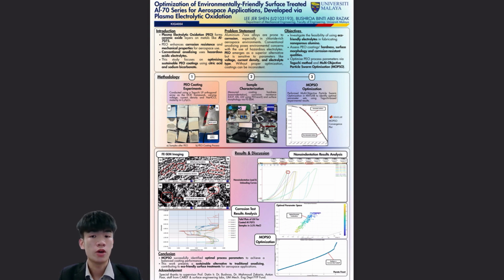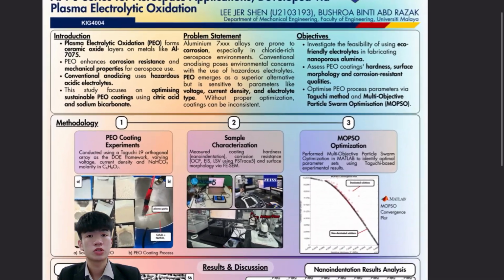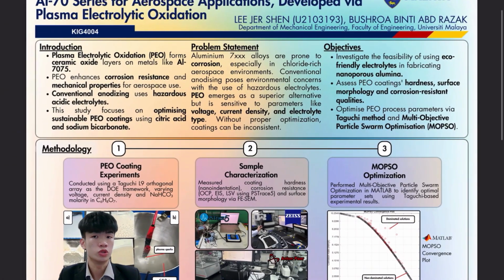Aluminium 7075 is widely used in aerospace applications due to its high strength-to-weight ratio and fatigue resistance. However, it suffers from severe corrosion, especially in chloride-rich aerospace environments. Conventional surface treatments like anodizing often fail to provide an ideal balance between corrosion protection, mechanical strength, and especially sustainability, as it relies heavily on hazardous electrolytes such as sulfuric acid and chromic acid.